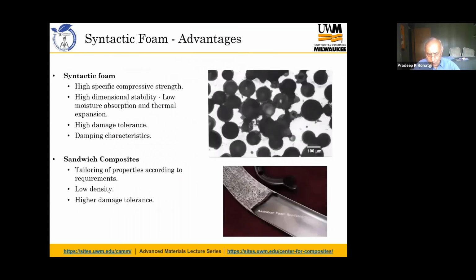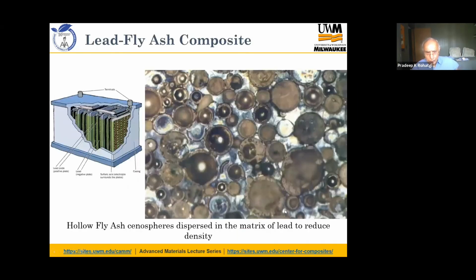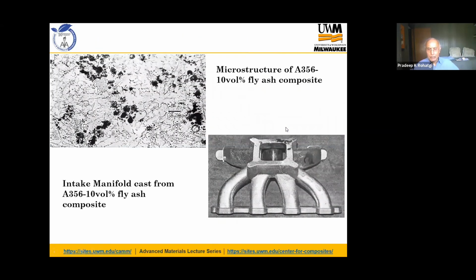Aluminum fly ash foams and other syntactic foams can be incorporated in hollow steel frames to produce lightweight frames for cars. In lead batteries, the problem is that they are very heavy, and we have shown that we can incorporate hollow microballoons in the lead tops to reduce the weight of lead batteries. This is hollow microballoons embedded in the matrix of lead.